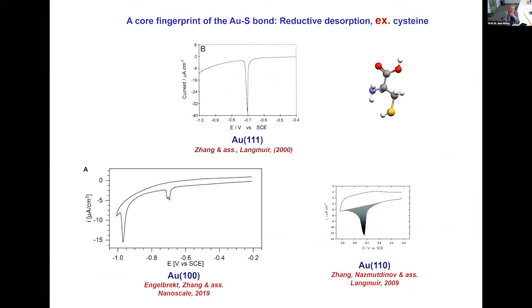A core fingerprint of the gold sulfur bond is exemplified by the amino acid cysteine. That is what we call reductive desorption, and I'll come back to this in a moment. There is a very sharp signal, provided it's a good surface and a good self-assembled monolayer. A very sharp voltammetric peak at a given potential. That's very useful because it can be used to tell us how many molecules are on the surface. We get a sharp peak if it is a good surface. If it's a poor surface, we get a broadened signal.